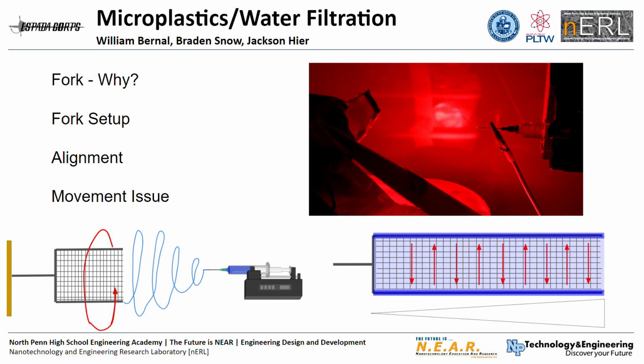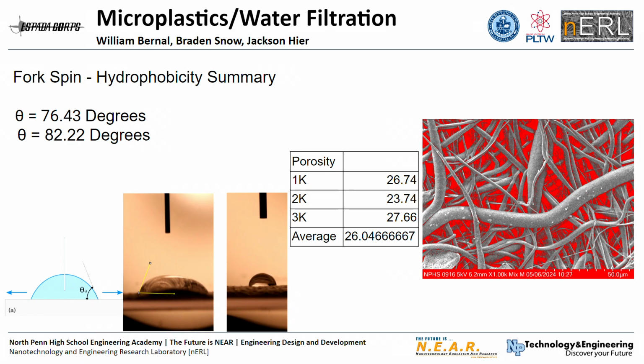And the next type of spinning we used was fork spinning. Fork spinning is a type of spinning that utilizes the bases of a very common type of spinning known as gap spinning, as well as drum spinning, as it has a rotating fork that contains the wires as well as 2 copper forks to create that conductivity and elongation and contraction of fibers that we're looking for to get a wide range of fiber sizes. Now, when looking at hydrophobicity, we weren't able to get it to be quite hydrophobic, but at the same time, it was hydrophobic enough that we didn't have to worry about it breaking down.